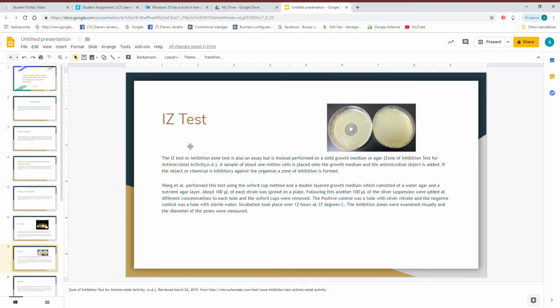So the positive controls were a hole with silver nitrate, and the negative control was a hole with sterile water. They incubated for 12 hours at 37 degrees Celsius also, and after the fact, the inhibition zones were examined visually, and the diameter of the zone was measured to get an account of the level of inhibition.